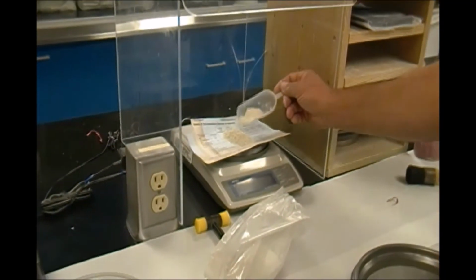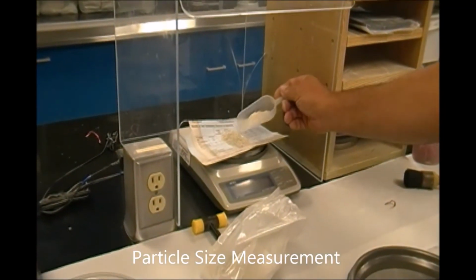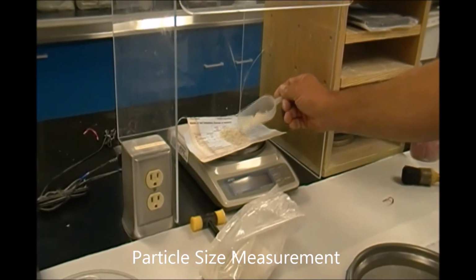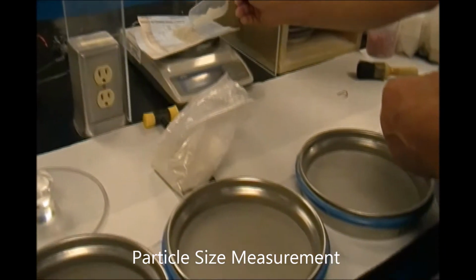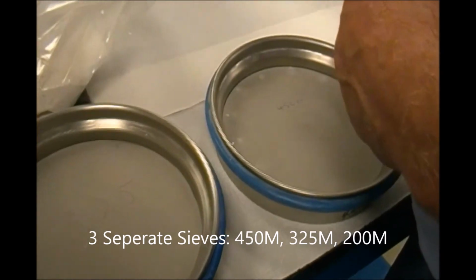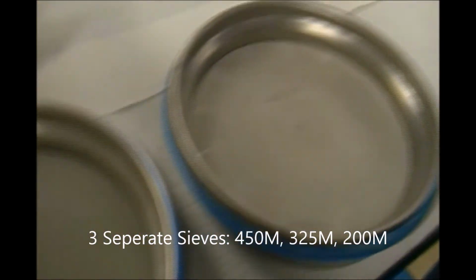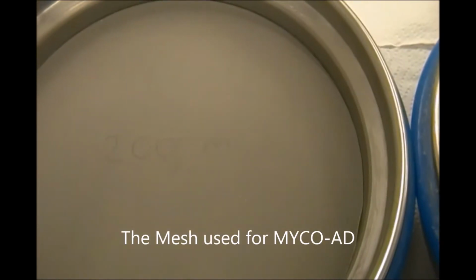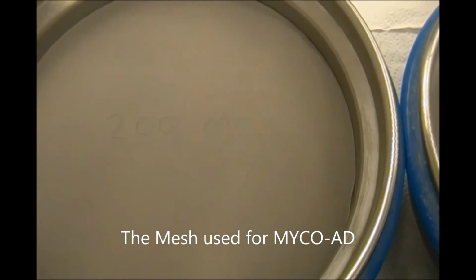In this area of the laboratory is where we measure particle size. What we will do is measure out 10 grams of the product. The product will then be put into one of these sieves, which is used for sieve analysis test. Each sieve is a different size. You'll notice here that we have a 450 mesh, a 325 mesh, and a 200 mesh. The 200 mesh screen is the screen that is used for MYCO-AD products.